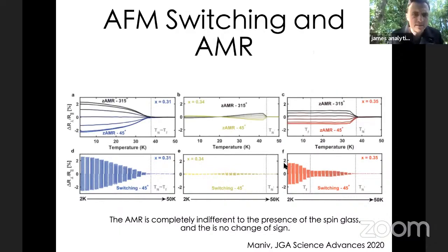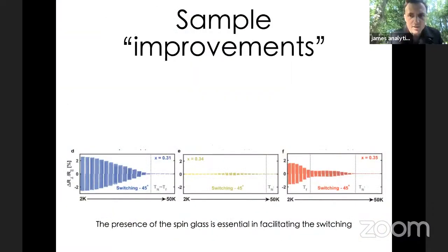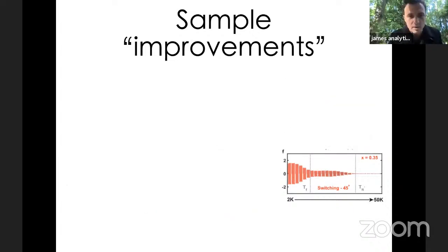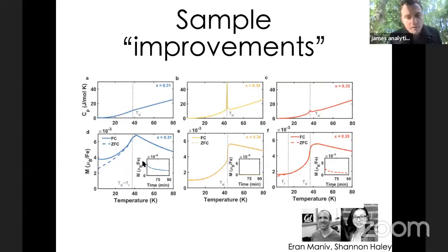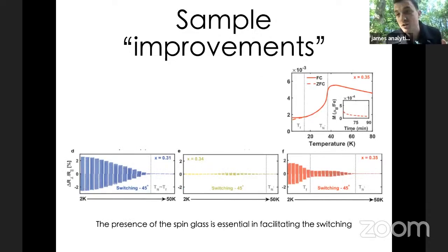But how does this relate to the other samples? Well, let me just go back a slide here. For the under-intercalated one, the splitting happens at much higher temperatures. So in other words, it becomes glassy very close to the Néel transition. So we probably wouldn't have noticed that difference. And for the perfect sample, the one right near stoichiometry, there's never any signature of any kind of spin glassy behavior. And there, we don't see any signature of any switching either. So I think disorder is involved. And I think that's very interesting.